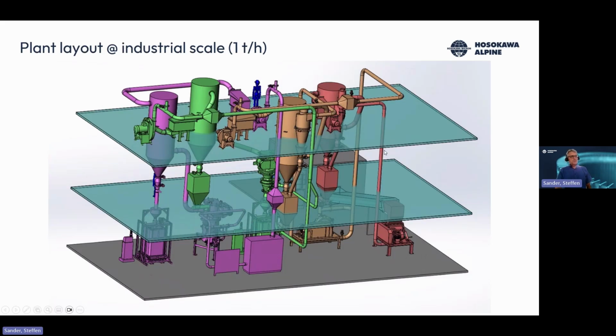You feed the material here into the cutting mill. Then you have here the impact mill, fine impact mill. After that, the classifier here, where you separate the material, the fine material that goes into this filter and then can be fed to the jet mill afterwards for further processing. This has to be decided in any case if it's really necessary to have a jet mill here. Maybe, let's say, a more cost-effective classifier mill could also do the job. That has to be decided case by case. But I think you get the concept.